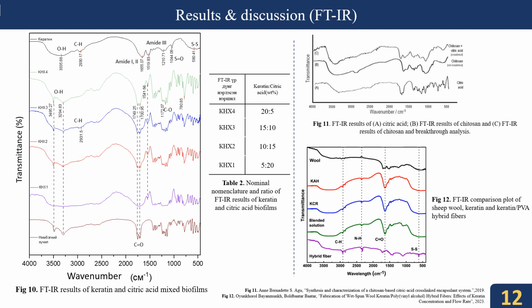The sharp peaks of the citric acid hydroxide bond, carbonyl bond, and C-O bond peaks of the citric acid are located at 1,389, 1,240 to 1,174, and 1,140, mostly after 1,000. However, the biofilm contains citric acid and keratin peaks, and the main change there, of course,